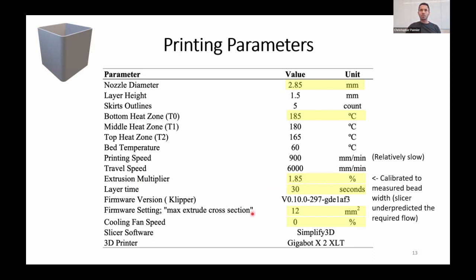Another thing that was frustrating was that we were running into errors while we were printing the tubes that we wanted to print. And when we tracked that in the code, we found out that the maximum extrude cross-sectional area default was 7, and we had to raise the limit so we're not faced with that error. So this is overall our printing parameters.